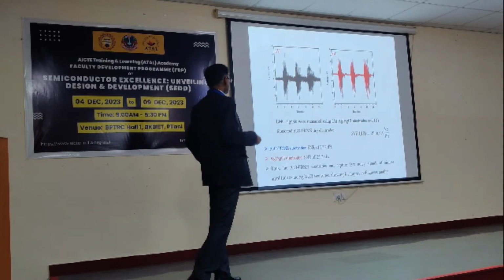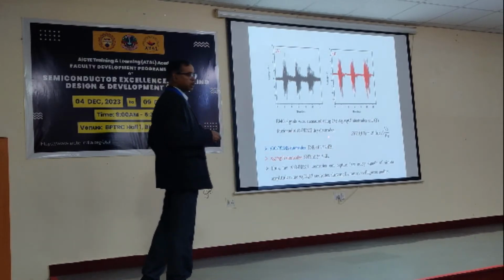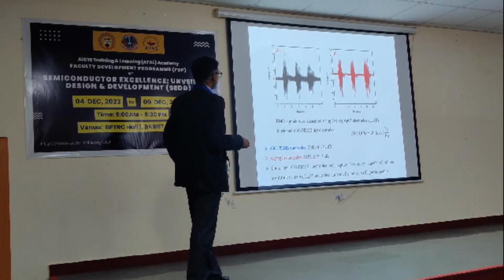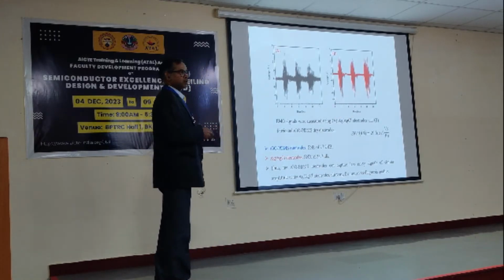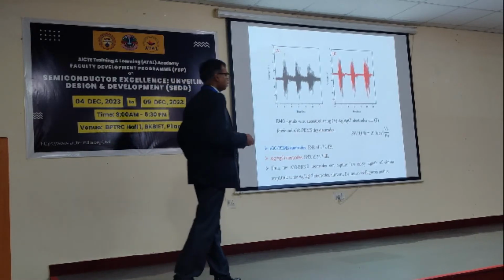You can see the peak to peak signal divided by this, so there is a lot of noise available. That is why this value for the reduced graphene oxide PDMS comes out to be 27.2 dB, while for the AgAgCl electrode, it comes out to be 25.7 dB. So this property also confirms that this dry electrode is an alternate choice and works very fine as compared to the already available AgAgCl electrodes.